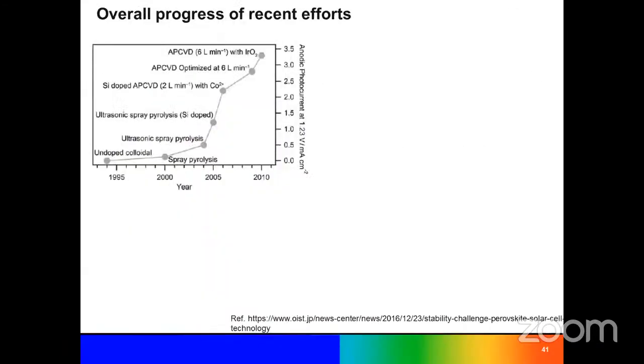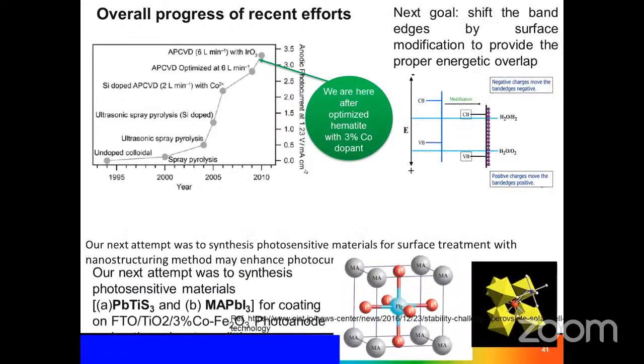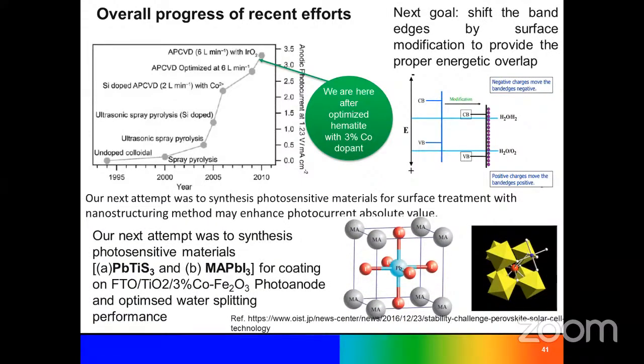So here, if you see in the literature with 3% cobalt doped hematite, where we stand in terms of anodic photocurrent is 3.5 milliampere per centimeter square. So we have to reach beyond that to get these devices commercialized. For this reason, we coated perovskite materials on top of these hematite materials for getting much more current density in this case.